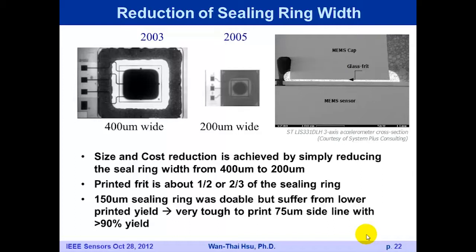And I want to talk about this glass frit, and this is a 400 micron wide sealing ring. And in 2005, we were able to reduce the sealing ring to 200. And the 200, I think, is very commonly used these days. And I had the opportunity of meeting a person who claimed he's the guy who did this 400. I just heard this as a story. He said he didn't really define it. He just drew it. So anyway, we didn't like this 400 micron sealing ring because it's really too big. So we were able to reduce this to 200 micron wide,